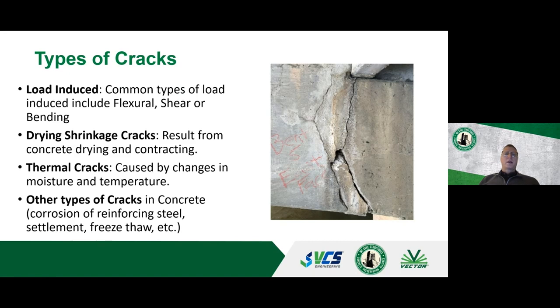It's not uncommon, as it's drying, for the outside of it, the surface of the concrete, to lose its moisture faster. We talked about that with plastic shrinkage cracking. So as it's losing that moisture, it's creating some internal tension because of that shrinkage. But the inside of that concrete element may still be under compression, so the forces are going otherwise.